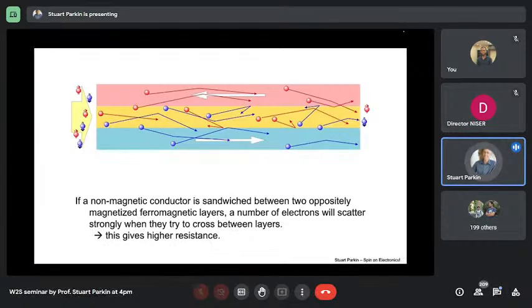So now you can create what we call a spin valve. A spin valve is shown here. You have two magnetic layers. The lower electrode shown in blue, the magnetization points to the right. The upper electrode magnetic layer shown in red points to the left. And in between, we have a copper layer. So now what happens when these two layers are aligned anti-parallel to one another, as shown here, then electrons in the blue layer are carried by, let's say, the blue electrons pointing up, and in the red layer, they're carried by the red electrons pointing down.